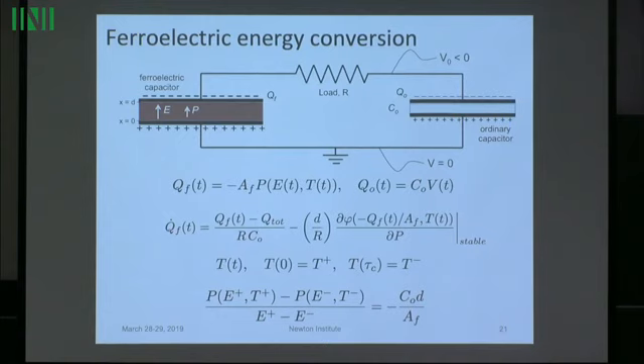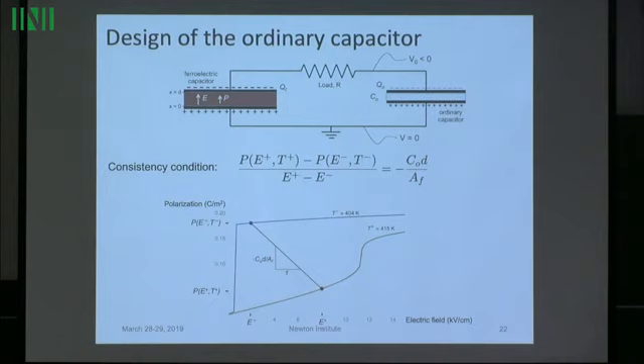So that condition says that the electric field at the high temperature and at the low temperature are related by, so this is at the high temperature, this is at the low temperature. The slope of this line is related to the capacitance of the ordinary capacitor. That just comes out from the ordinary differential equation. So, of course, in this device, we want a very big change in polarization. So the design criterion is that the slope of this line is minus the capacitance of the ordinary capacitor times the thickness D divided by the area of the ferroelectric capacitor.